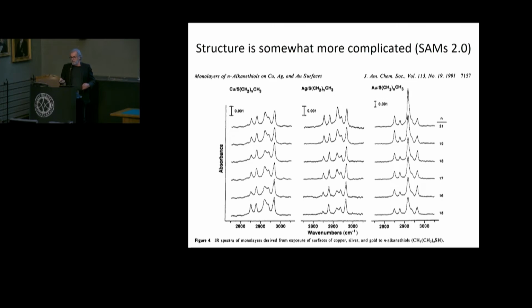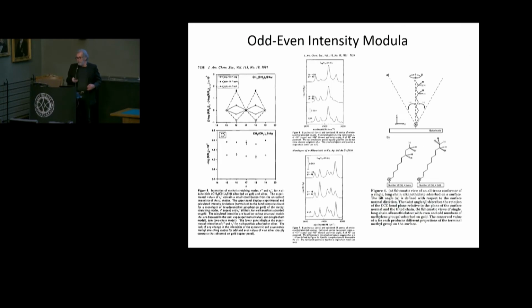And you find, as a function of chain length, that you have a similar structure, and it's a beautiful thing that you can then reduce that to a set of arguments as to whether or not the chains are along the surface normal direction, or do they have a slight cant from the surface normal direction. And we found, for example, that they have a cant off the surface normal direction, which is larger on gold than it is on silver. But in gold, that orientation is fixed. It only goes in one direction, so you see a sign of an angle there, where chains are rotated azimuthally and then tilted. And we call these alpha and beta as the characteristic angles of the single chain structure. And they only go in a certain direction on gold, and that makes a determinate projection of the methyl group at the chain end at the ambient interface.